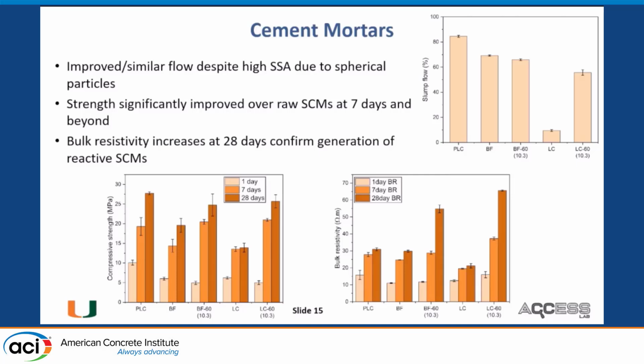We see in compressive strength that over 7 days, significant improvement beyond the raw supplementary cementitious materials, the raw inert fillers, and the mechanochemically activated materials. Also at 28 days, we see this sharp increase in bulk resistivity with respect to the control and with respect to the unactivated materials, which confirms again that we've generated substantially reactive SCMs.